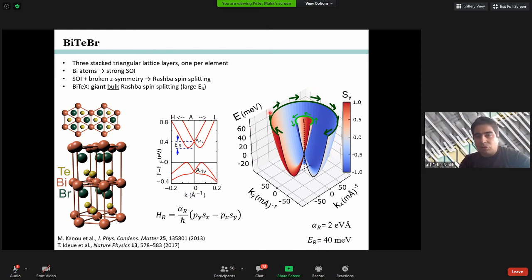Here is the Rashba band structure again. You have seen this once or twice today already. Just the main feature: if you are at really high energy, there are two Fermi surfaces. In both you have spin locked to the momentum. The chirality is opposite. The spin is winding always perpendicular to the momentum. And at zero magnetic or electric field, there's zero spin polarization in this material.